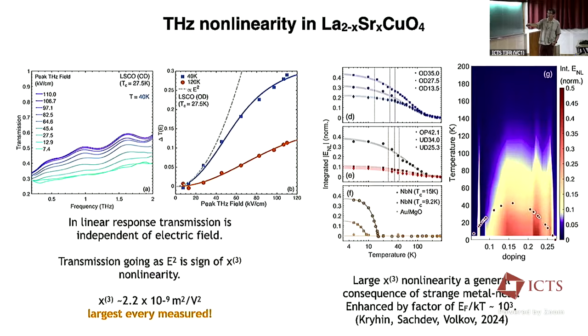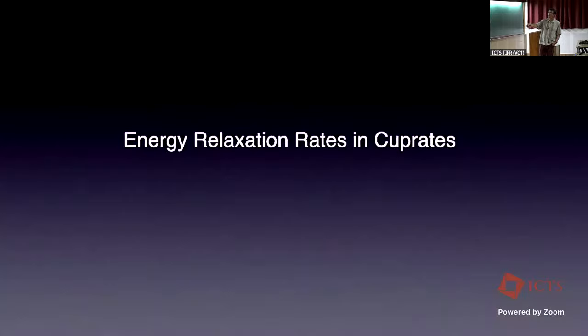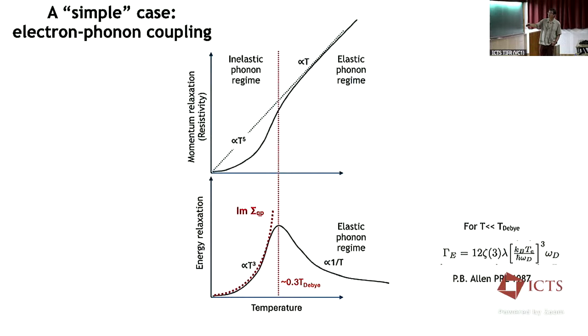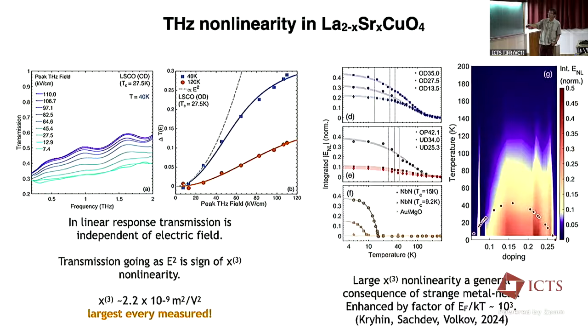When you do this analysis on the cuprates in the normal state, you get this number here, which turns out to be the largest nonlinear susceptibility, the Chi3 susceptibility, ever measured. I mean, it's orders and orders of magnitude larger than in the normal optical range where nonlinear optics is usually performed. Previously, the largest nonlinear susceptibility was in graphene, but this is now, if you will, superseded by the cuprates.